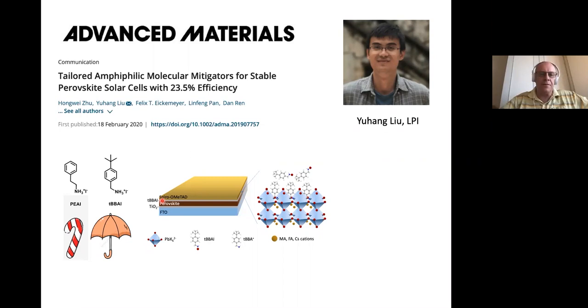What was developed here was this tert-butyl structure, which works as a kind of an umbrella in the passivation molecule layer. So we obtained two things with that. One is to passivate recombination centers and extract holes quicker. And the other one is also that this is a hydrophobic molecule.